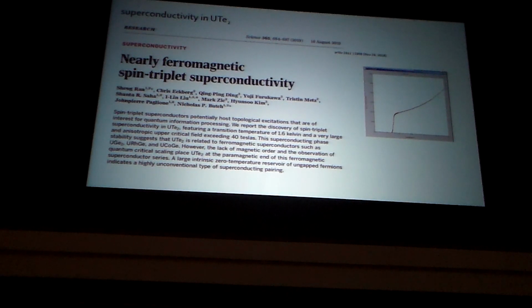But there are very few spin triplet superconductors. Spin triplet means, of course, the spins are aligned this way, and you can compare that to the singlet, where they're opposed. And that means that the orbital symmetry has to be odd, so it's typically p-wave, you have p orbital things. And with p orbitals, you can have all sorts of possible superconductor wave functions. I won't get into that, but who cares whether there's a triplet? Well, Chandra gave a talk a couple of weeks ago where if a spin triplet superconductor is topological, it possibly could be used in quantum computation. And of course, possibly means there's a long way to go.